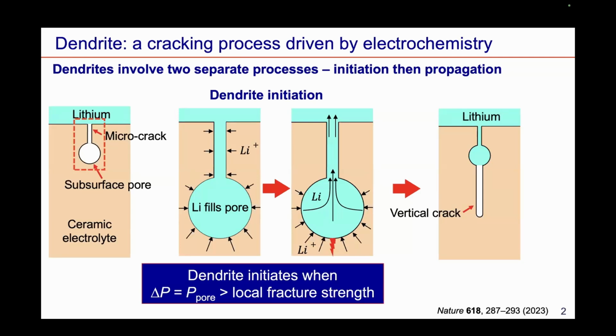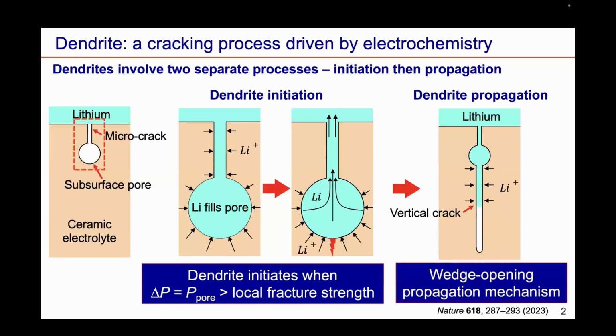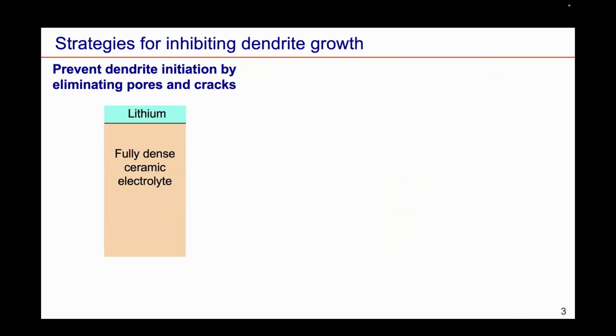If we further deposit lithium into this pore, the lithium will be deposited along the lateral interfaces of this micro-crack, inducing a pressure buildup and leading to crack propagation. So this is just a wedge opening mechanism for crack propagation and dendrite propagation. Based on this mechanism, we can prevent dendrite initiation in a 100% dense ceramic because there are no subsurface pores and micro-cracks.